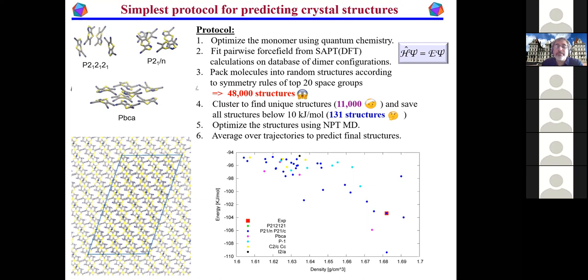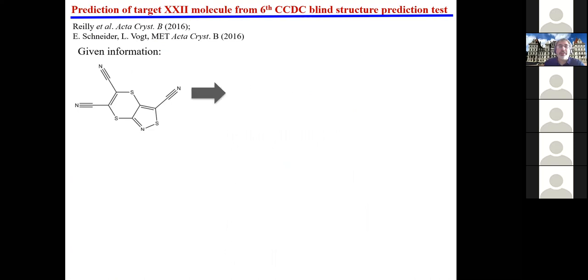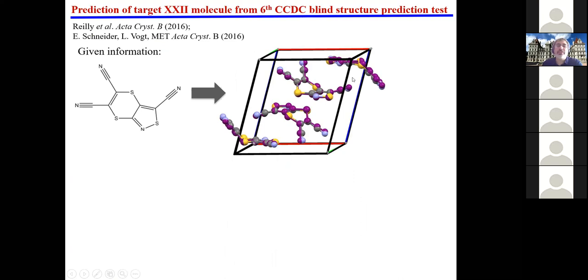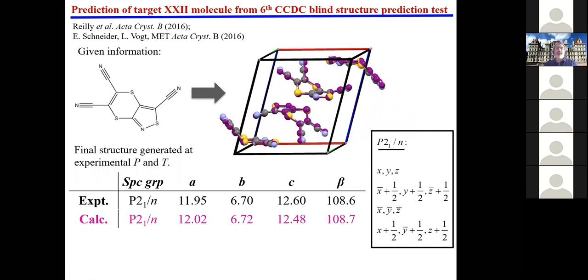And so just to remind you, you start here with this chemical diagram, and what you have to get to is this prediction, all right? And so that's what's being shown here. That is an overlay of the predicted structure and the experimental structure, all right? Turns out it's a P21/n structure, so these are the symmetry operations. The agreement between the experimental lattice parameters and the calculated ones is very good. The better measure of how well you agree is the RMSD20, which they take 20 molecules out of your structure and 20 molecules out of the experiment. They align them, and then they do an RMSD of that alignment, sort of like what you do when you do protein structure prediction. Well, at 300 Kelvin, if you thought that was where the experiment was done, the RMSD20 is about 0.187.